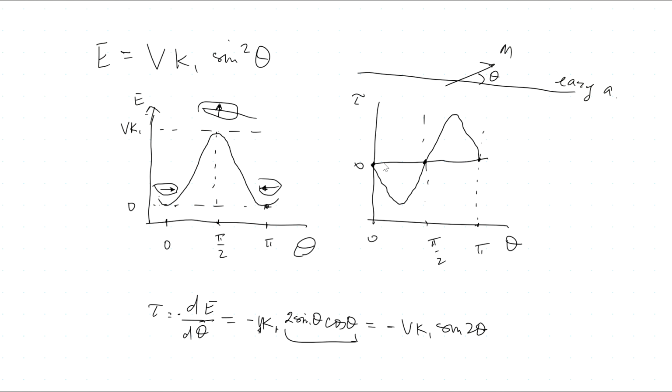So that is actually widely used. You know, all information in hard disk drives is stored in the form of magnetic domains. So if you have anisotropy, you can get a stable state pointing in this direction and a stable state pointing in that direction. Then they're equally stable. This would be your logical 0. This would be your logical 1 to store information.